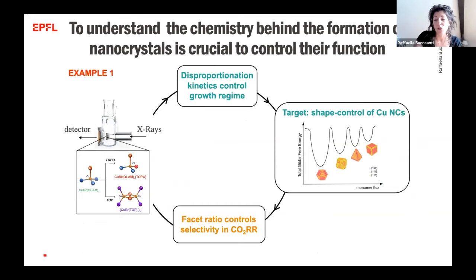So this was basically the first story that I wanted to share with you, where we did look into the type of intermediate. So we tried to understand the chemistry which is behind the formation of nanocrystals. We discovered that these ligands do react with the precursor, and they form clusters, the molecular complexes. And it is the disproportionation rate of these molecular complexes that eventually matters in determining the growth regime. And learning this, we could access different shapes of nanocrystals and demonstrate that facet ratio controls selectivity in CO2 reduction.